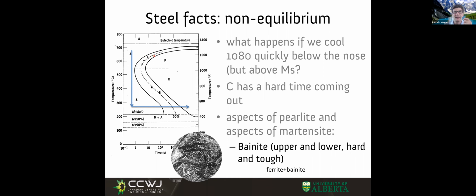We know that at high temperatures, we're gonna get coarse microstructures. At low temperature, we're gonna get fine microstructures. We know that if we quench really quickly to room temperature, we're gonna reach martensite in most steels. Again, everything has a counterexample, but in most steels, if you quench to low temperatures, you're gonna reach martensite. And if you hold at low temperatures, you're gonna find bainite. There is some sort of convenient hybrid. Very, very interesting.